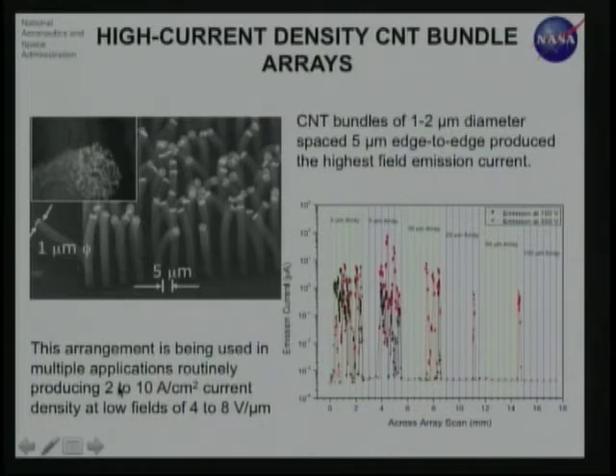About 2 to 10 amps per square centimeter routinely is what we get for very low applied fields, at 4 to 8 volts per micron, which means if you make a device that's only about a micron away anode to cathode, then you can pretty much apply digital voltages less than 5 volts and achieve the kind of current densities that you want.